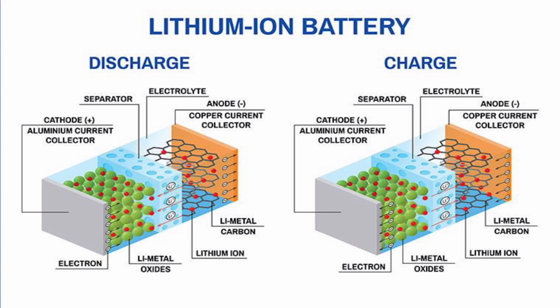Step 2, formation of SEI and CEI. In the very beginning of the first charging process, electrons migrate from the positive electrode material (oxidation) through an external conductor into the negative electrode material (reduction). To ensure charge neutrality, the lithium ions deintercalate from the positive electrode material into the electrolyte and migrate through the electrolyte to the negative electrode material for subsequent storage. As a result of these reactions, boundary phases, so-called SEI and CEI, are formed at the interfaces between the electrolyte and the negative electrode surface, and the electrolyte and the positive electrode surface, respectively.